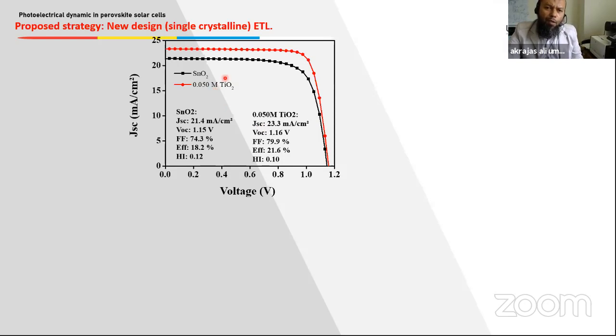We compare the performance with SnO2. Why do we compare with SnO2? Because SnO2 is much superior in properties compared to TiO2, such as SnO2 contains less defect density, and also SnO2 has much better hole blocking capability. So it is worthwhile to compare between these two materials. Then we get efficiency for the SnO2 based device of only 18.2%, which is much lower than the nanograss based device.